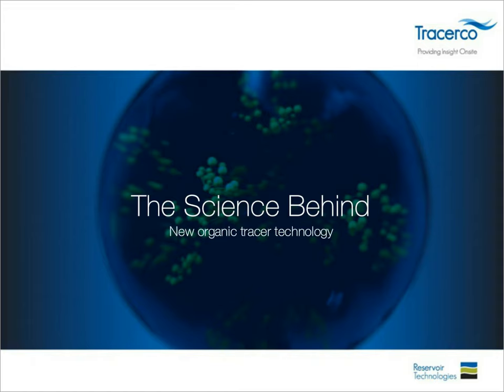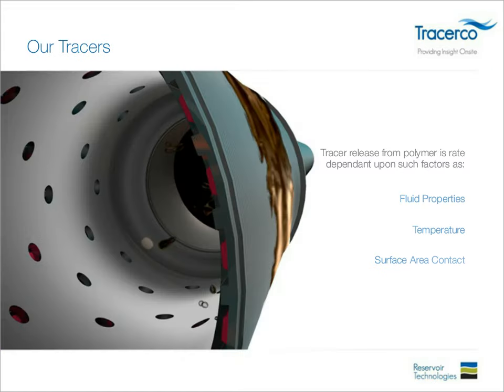So the science behind tracer release depends on a number of factors. Fluid properties are important, whether they're heavy oil or light oil. Temperature has an effect, so the higher the temperature, the more tracer is released from the polymer. We also have the surface area contact, which is extremely important, as this dictates how much of the tracer in the polymer is exposed to the targeted fluid. And we measure the amount of elution, as we call it, or tracer release of molecules, in milligrams per centimetre squared per day.